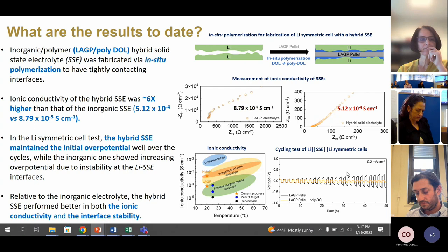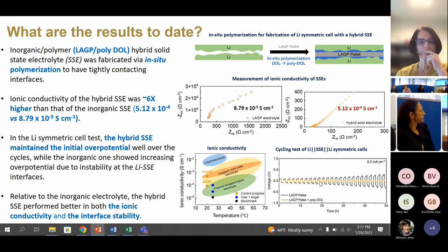The cycling test and stability. Basically, what you can see here is the overpotential. When you cycle through batteries, as you start to see this diverging voltage, that means it's no longer stable, and then the cyclability will be poor and the performance will suffer. So that was the LAGP, the black. If you look at the LAGP hybrid, it remains stable throughout, I think this was 50 hours, and I think it was two cycles per hour. So over 100 cycles already, we're seeing large stability.